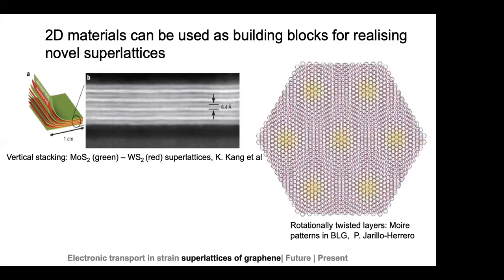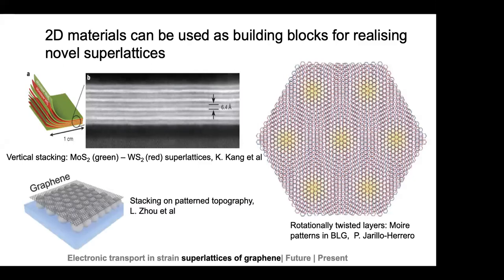Unmesh spoke at length about this system, twisted bilayer graphene, and it has generated a lot of interest currently, especially because of these moire patterns which are generated all over the system, and that comprises a superlattice structure. Then you can have strain generated in any of those systems because of lattice mismatch or because of some sort of topography below it. And that is another method of forming superlattices, by stacking a 2D material on top of a patterned substrate.